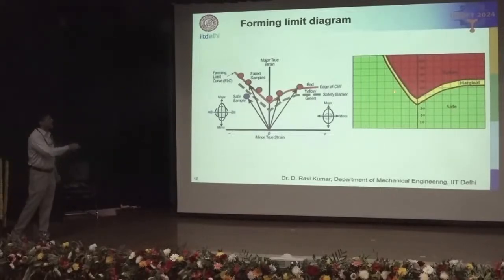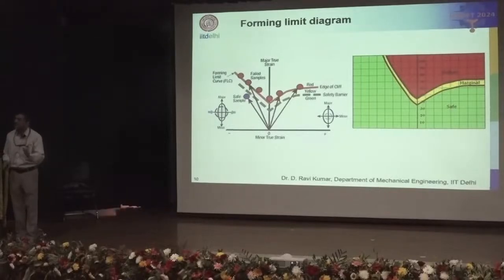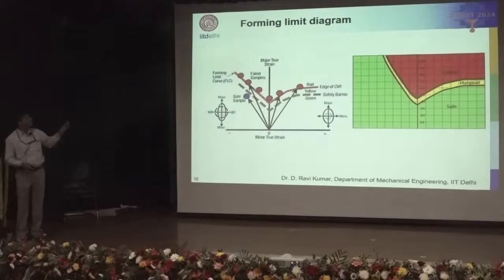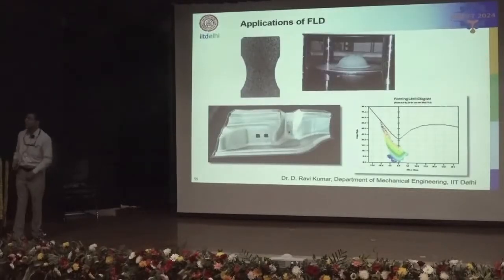So that is how the forming limit curve is plotted, but it doesn't come from any one single test. We need to carry out a large number of tests. The most popular method is the Nakajima method, using which we can evaluate the limit strains in different modes of deformation by changing the geometry of the sample. Okay. So where is it useful? How can we use this forming limit curve?